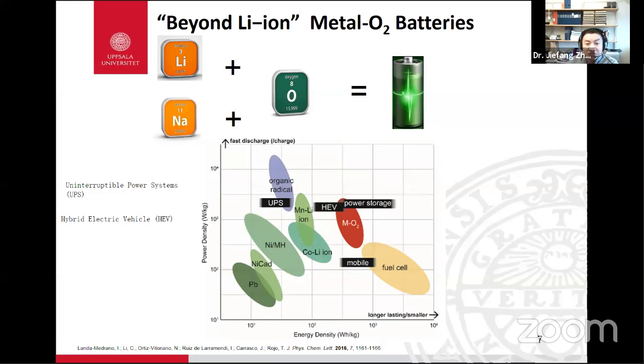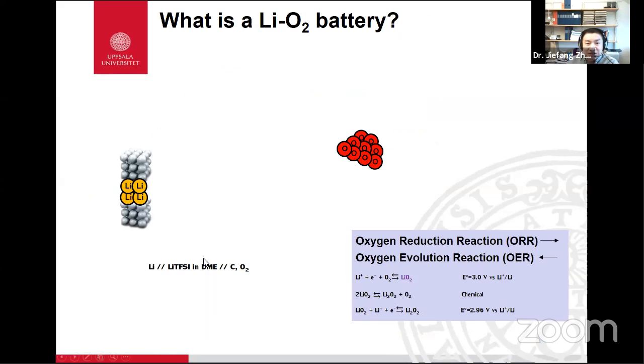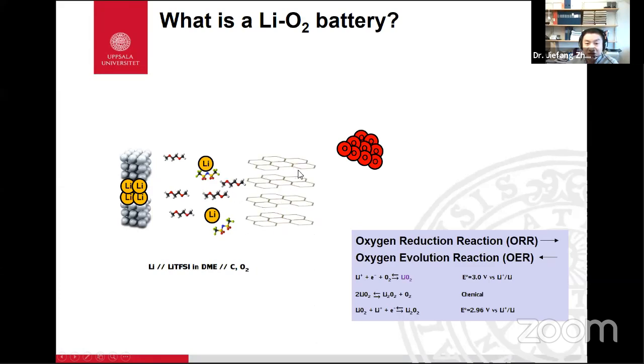The metal oxygen battery is one category inside. You can see the metal oxygen battery has very high energy density, which is close to a fuel cell, and also comparable to gasoline. So this is the mechanism for the lithium oxygen battery. In the anode part, it has the lightest metal, lithium, and in the cathode part, the active component is oxygen from air. So sometimes we call it a lithium air battery. That's why it has such high energy density, because this is the lightest metal and this is just air, the gas. We have the lithium-containing electrolyte between them, and also a cathode support.